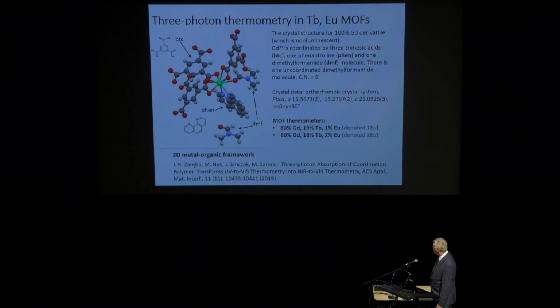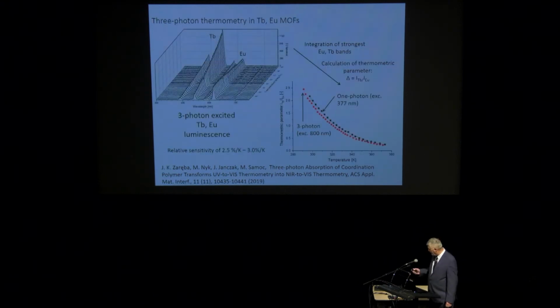This pair, terbium and europium, is a very typical pair for remote thermometry. And indeed, the spectra that we see here, in this case, we are close to room temperature because we are interested in the biological range of temperatures. So close to 37 degrees, right? A little bit more, a little bit less. And indeed, in this range from 0 to 100, these are not Kelvins, these are Celsius, centigrade, okay? So this is the biological range.